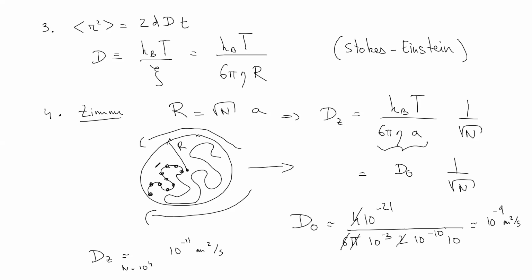For instance, if I'm really in a solution with only one chain, it's a dilute solution. Here I have solvent molecules all around and no other chain. One can show that by hydrodynamic interactions, this polymer chain is dragging fluid with it, and it behaves mostly as a big sphere that is rigid with no fluid flow inside. Okay, so that's a good description for solutions, and here dilute even, because I have only one single chain.